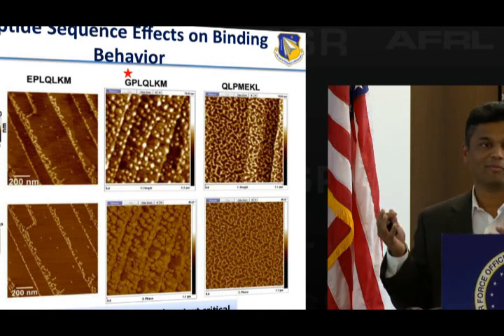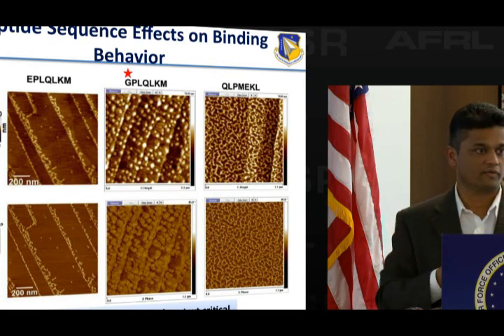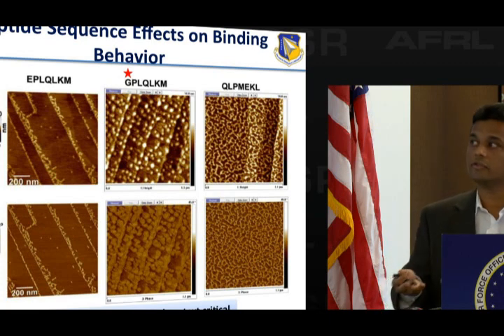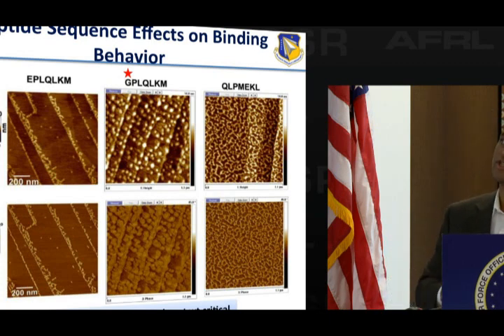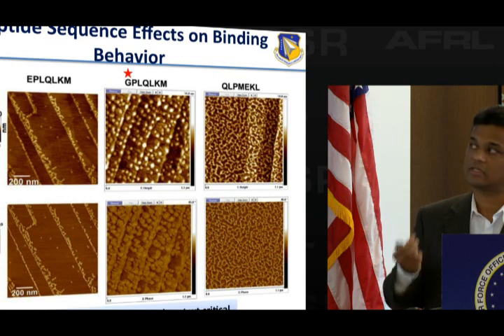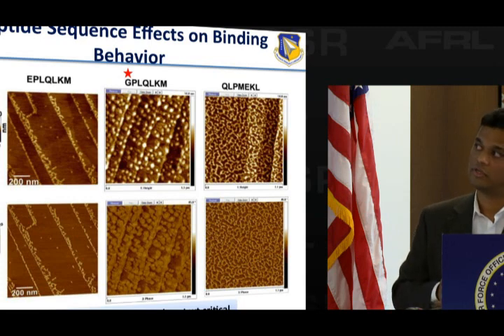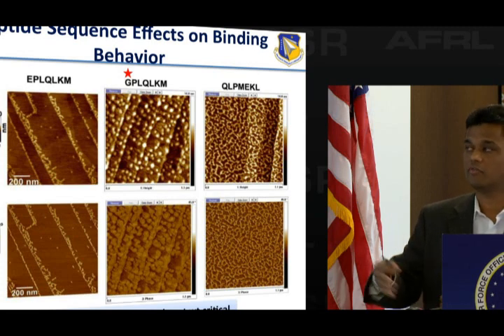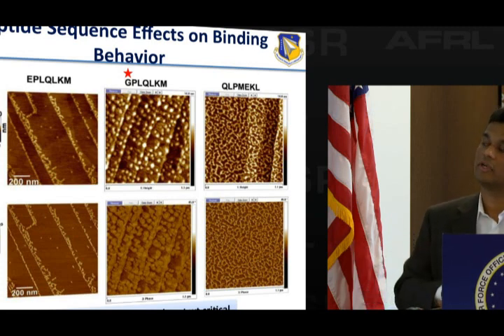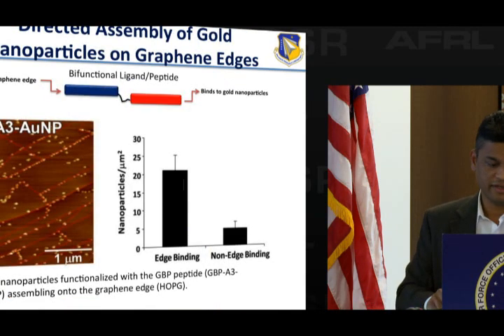So just putting amino acids together, you might think an aromatic residue should work well when binding to a graphene surface, a carbon nanotube surface. I'll just throw that and they'll bind. It's not the case, okay? Because this is evolved through the evolution in a test tube method, and you get very highly specific sequences that have an affinity for your surface. This is done in the drug industry normally, and other genetic tools have been used that use combinatorial approaches to identify highly specific sequences. So the take-home message from this is that amino acid composition and context is critical for the binding onto a graphene surface.